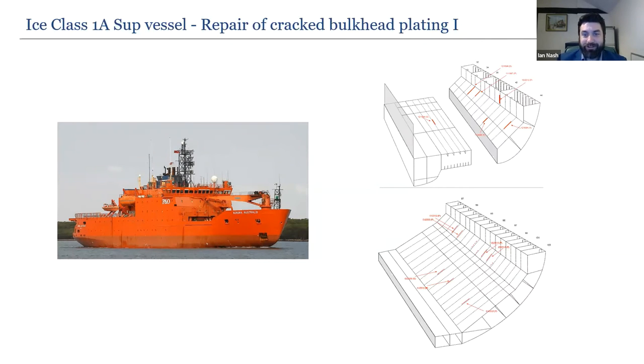In summary on cracks: initiation is primarily due to decreased structural steel thickness resulting in increased stress at critical sections. Ship protective coatings are incredibly important — corrosion can only take place once these are damaged. Ship structures are subject to cyclic stresses from wave pressure, ship motions and loading conditions, making fatigue an important design criterion. The science of cracks is important to forensic investigators, insurance surveyors, class surveyors, port state control and other maritime agencies for assessing seaworthiness.